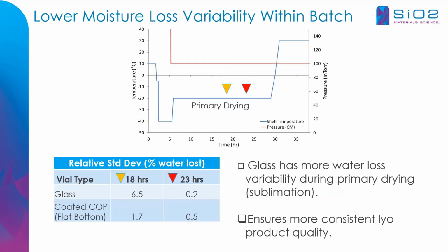Again, another feature, because of the consistency of the container, is the consistency of how the product dries, the primary drying, because that also has an effect on the cycle. And so we have a much more consistent drying. We've looked at the water loss after 18 hours and 23 hours, comparing the SiO2 flat bottom container against glass. And you can see that the amount of water loss is much more consistent with SiO2 versus glass.